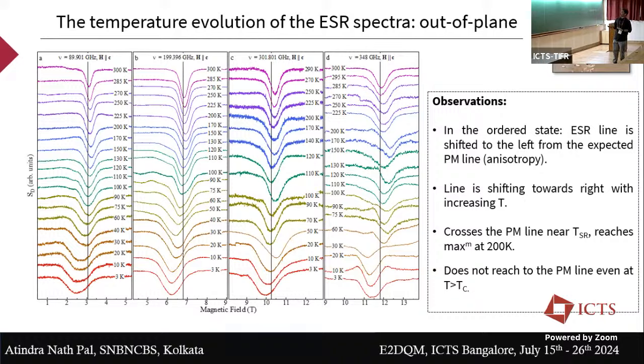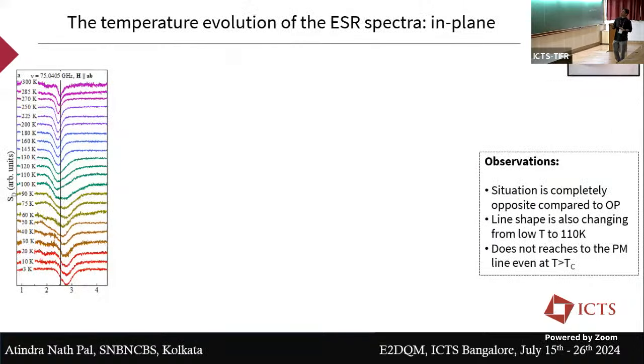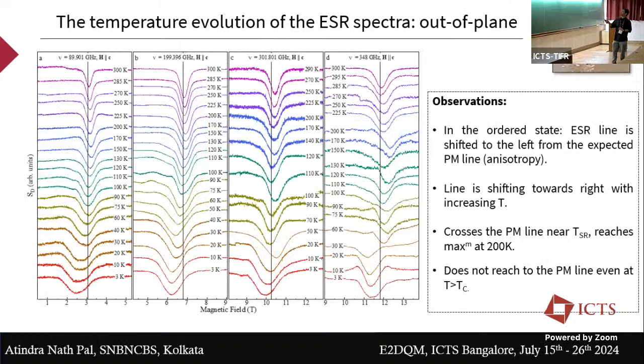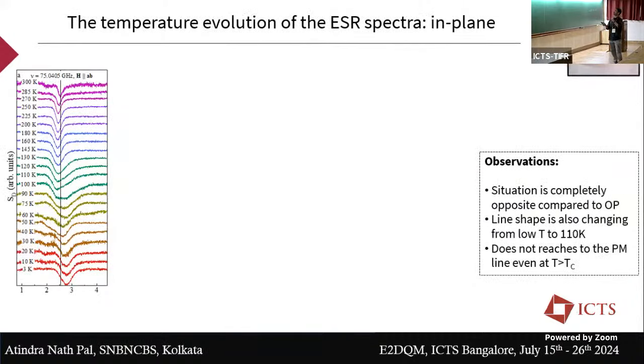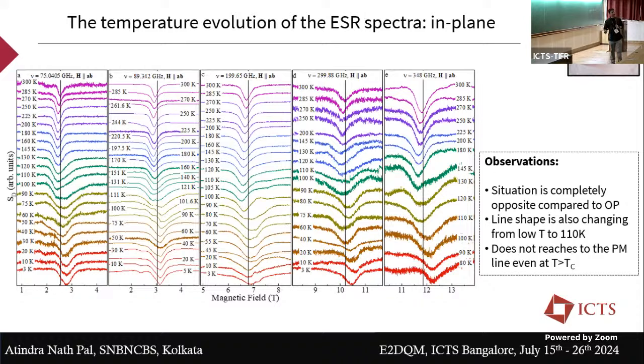In the previous measurement, the magnetic field was applied out of plane, that means in the C direction. Now if you do the same measurement with the magnetic field applied in plane, you get spectra where the shift is in the opposite direction, and you observe exactly similar kind of data. As a function of frequency, you see a similar effect, so it's almost a frequency-independent effect.